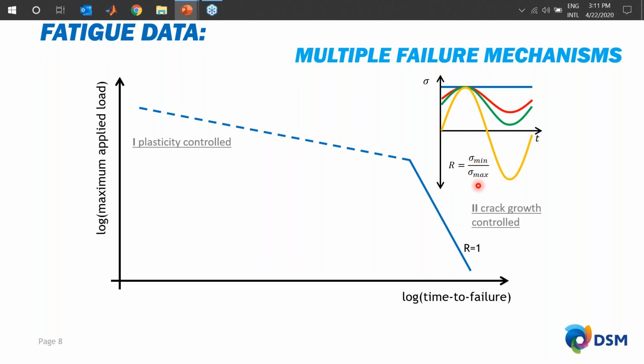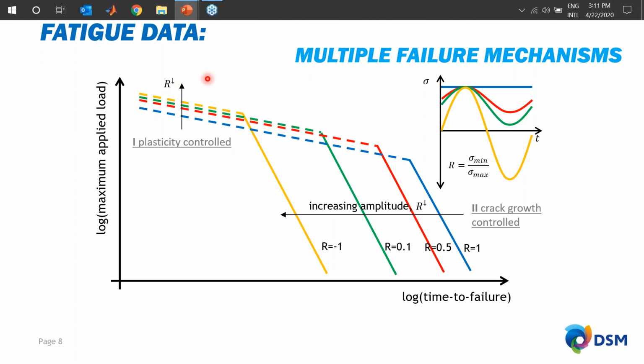so the minimum load divided by the maximum load, you can imagine if this R value is equal to 1, you just have a static load since both loads are equal. And if this R value is decreasing, you gradually increase the load amplitude. But if you do so and you look at the fatigue performance, then you see something nice appearing. Because for this creep controlled region, you see an increase in lifetime with decreasing R value or increasing amplitude. And at longer lifetimes and lower loads, you see the steeper region actually shifting towards lower lifetime. So you see that for the fatigue controlled failure, lifetime decreases with increasing amplitude or decreasing R value.